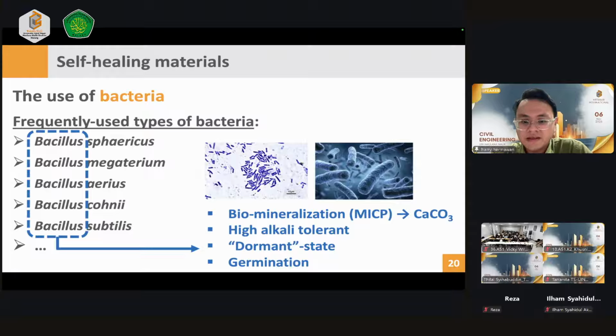This is important because when we incorporate the bacteria into the concrete, it is a very alkaline environment. So we have to ensure that the bacteria will survive in the high alkaline environment of the concrete. And with this Bacillus bacteria, the bacteria will remain stable inside the concrete materials. And if it is not being used, it will stay in the dormant stage.